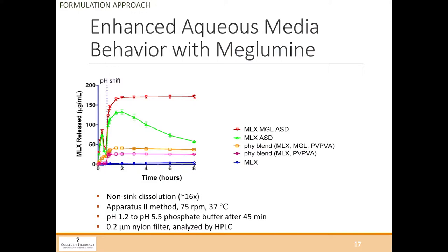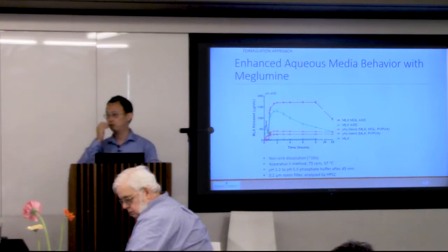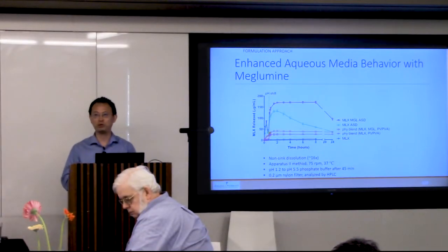Meloxicam solubility is quite low, even at pH 5.5. So when we have this amorphous solid dispersion with meglumine in there, they actually stay supersaturated much longer. Now I want to clarify one thing. When we take a dissolution sample, it goes through a 0.2 micron filter, so the concentration here is actually free drug, nanoparticles, everything in there. It's not necessarily just free drug only.